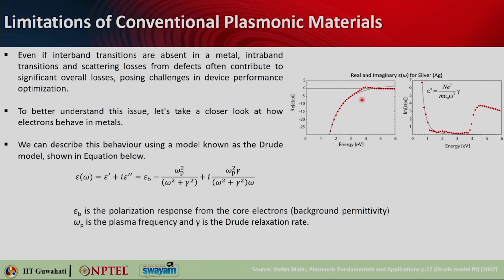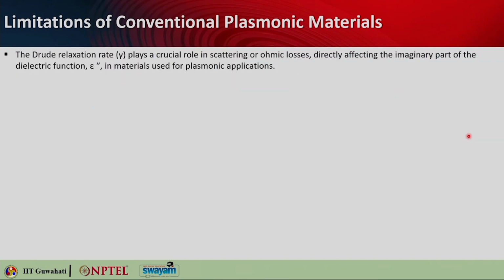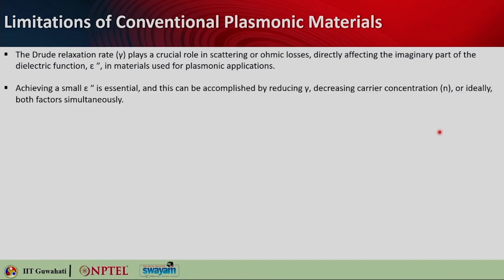So when you plot this, the dots show the real values, the experimentally measured values, and the curved line comes from this particular equation. On the other side, this is the imaginary part, epsilon double prime, and you can see that it also closely follows the experimental data up to a particular wavelength or energy range. Now, what is important to note here is that the Drude relaxation rate, gamma, plays a role in the scattering or ohmic loss, because it directly affects the imaginary part of the permittivity, which is epsilon double prime.